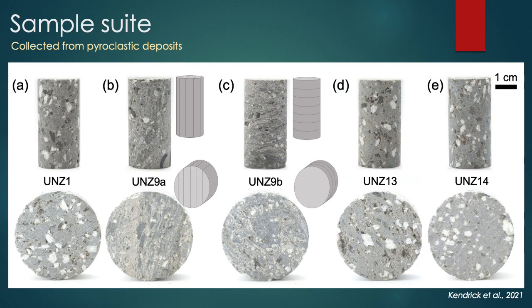From the collected samples, we selected 5 sample groups indicated in this image for the remainder of the study. These represented a low, medium, and high porosity sample, as well as an anisotropic banded sample cored in two orientations to the fabric, as such heterogeneity is commonplace in the Unzen lavas. Here you can see both cores and disks for compressive tests and Brazilian disk tensile tests respectively.